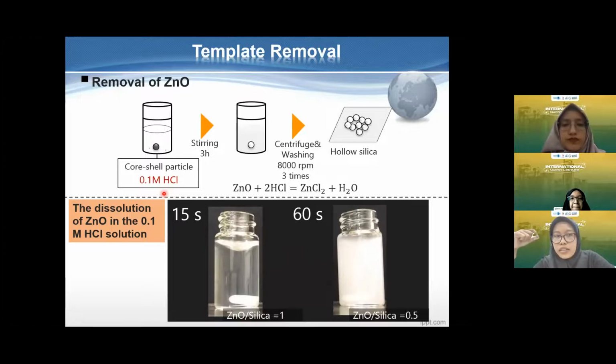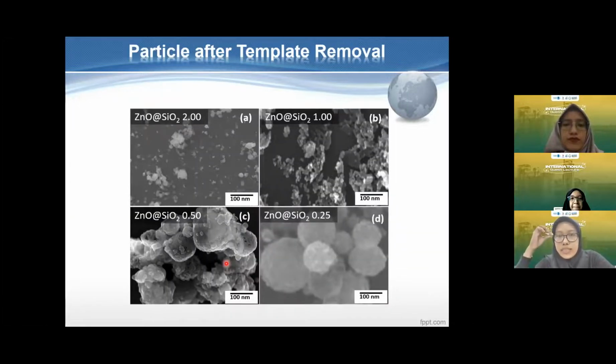It shows that the zinc oxide particle is already removed from the inner part of the composite particles, because the silica particles are the transparent one. So if we put it in this solution, the solution consists of the silica particles, but the zinc oxide particles are already gone. So this is after zinc oxide removal. There is no big particle here, only the small size, because the zinc oxide is already removed from the particles.